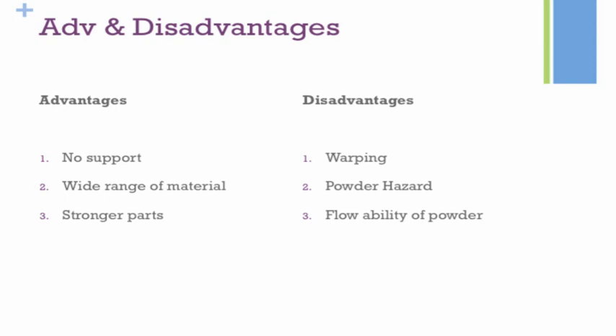Moving on to the advantages and disadvantages of the SLS process. Firstly, no support is required, because the surrounding powder is actually supporting the model — so there are no overhang issues. Next, a wide range of materials can be used. Most materials in powder form can be sintered depending on how powerful your laser is. For polymer you need a certain laser power, and for metal a higher powered laser. One thing to note is that for laser sintering of metal, you can coat the metal powder with polymer, so what you're actually sintering is the polymer and not the metal itself.